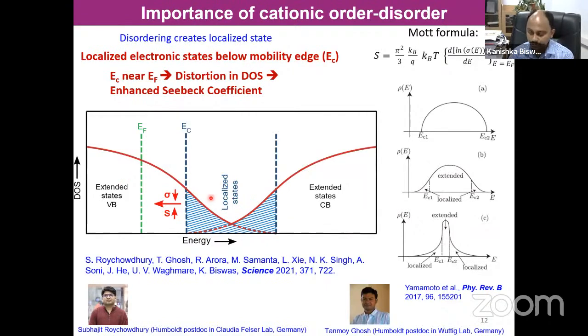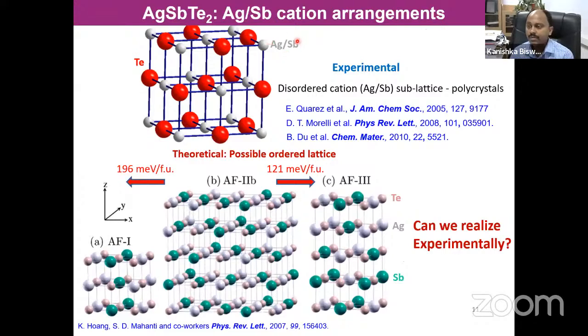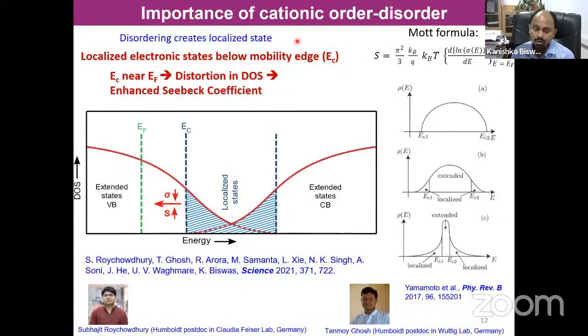Now I have AgSbTe2, which has silver and antimony intrinsically disordered. So I have a lot of localized states in this compound, which is not good for thermoelectrics, because if my Fermi level, which is nothing but how much the holes fill up or the electrons fill up in the conduction band or valence band, falls inside the mobility edge, the electrical conductivity vanishes. I have an electrical insulator, which is no good for thermoelectrics. So basically this Anderson localization is no good for thermoelectrics.